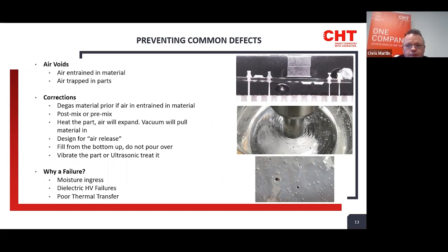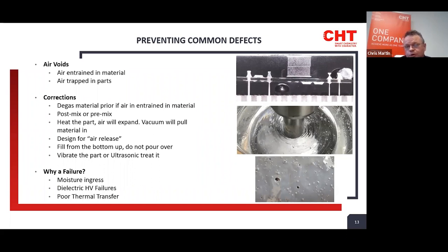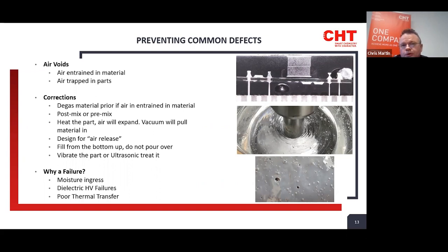What failures would you likely see from air in the potting? First, moisture ingress — air voids can be a weak point allowing moisture in. You can also get dielectric failure, where arcing occurs across the bubble. And air is not a good thermal transfer material — it insulates. By having a solid mass of silicone there, you'll get better heat transfer.